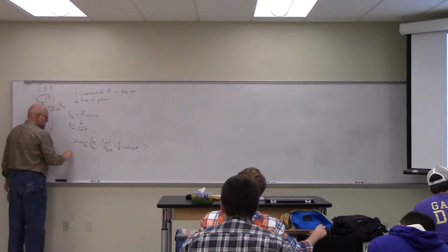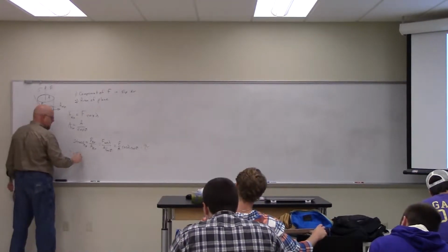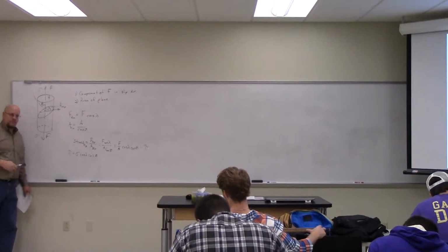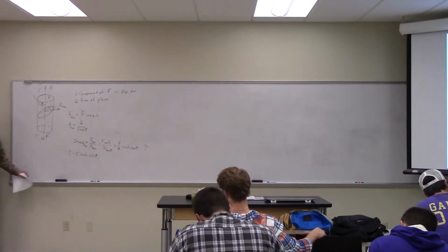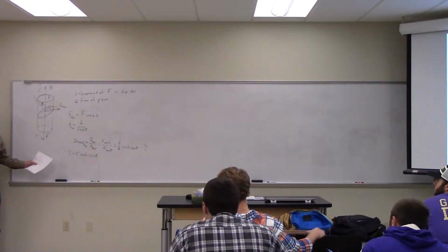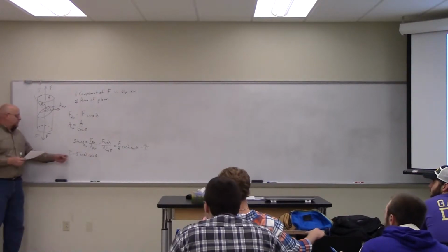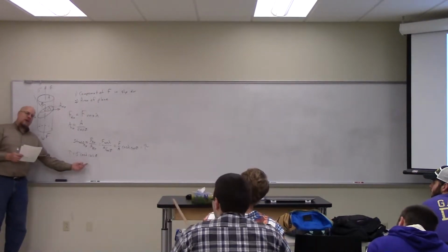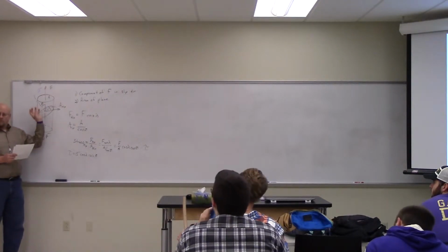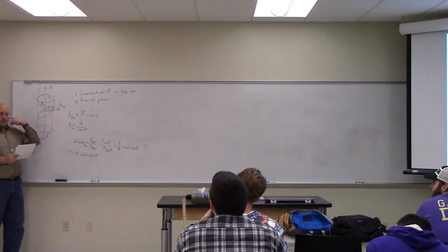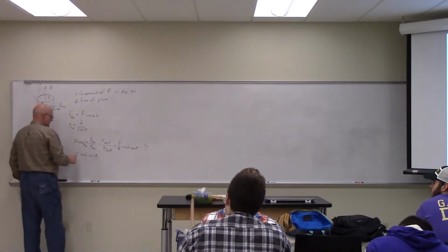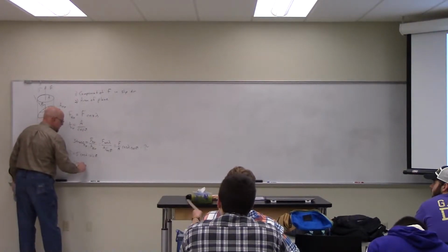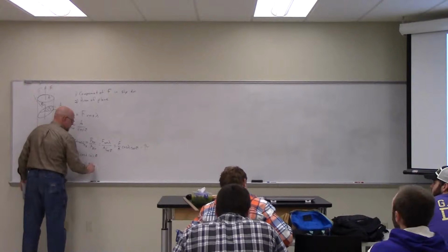So the shear stress is therefore equal to the applied stress times the cosine of lambda times the cosine of phi. We follow that? So what we end up with is a shear stress locally that is determined by the applied tensile stress and the orientation of the crystal. Okay? We call that the, I'm putting critical in parentheses for a reason, the resolved shear stress.